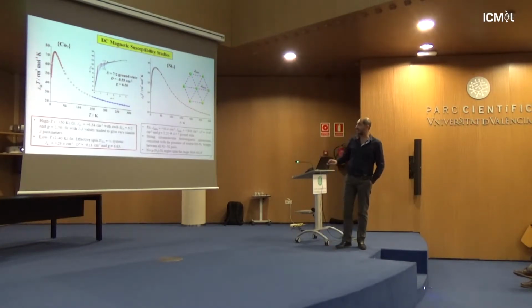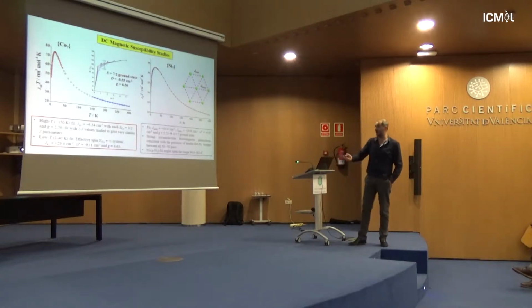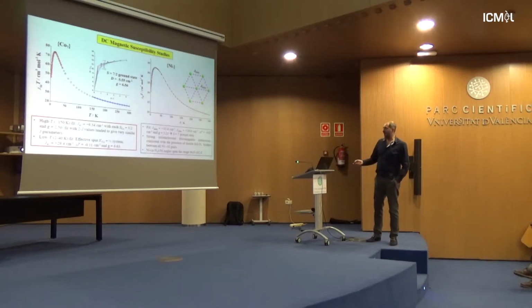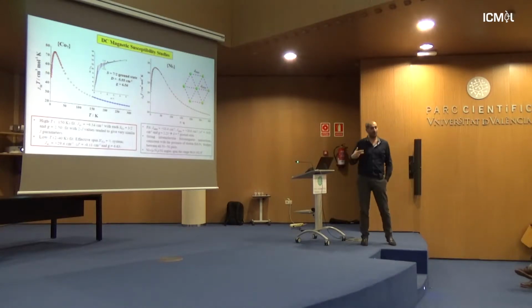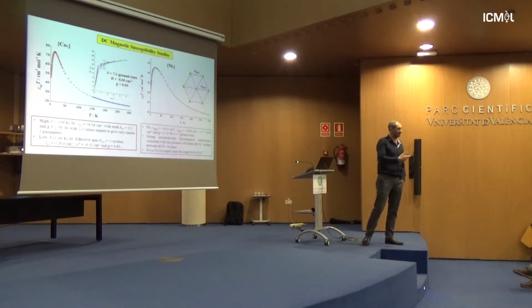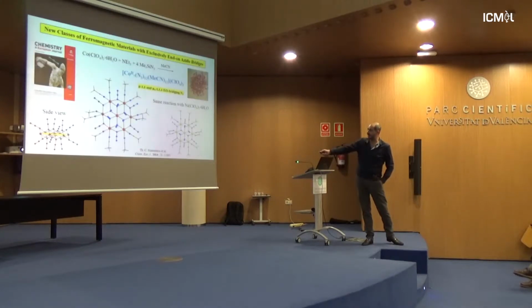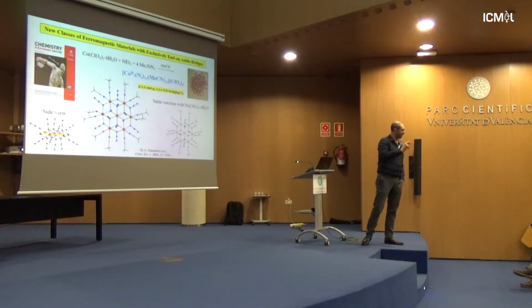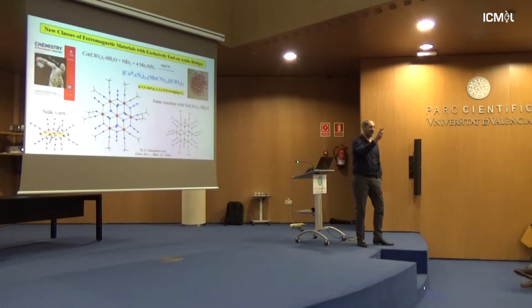It was easier here in the nickel-7 because of the lack of that large anisotropy that we have in the cobalt-2+ ions. We got the J values here, which are both positive. The S equal to 7 spin ground state for the nickel-7 compound, and these can all be confirmed by magnetostructural criteria. If you look at those nitrogen-metal angles, they are all below 104 degrees, which is the cut-off, as we say, edge between the ferromagnetic to anti-ferromagnetic switching.